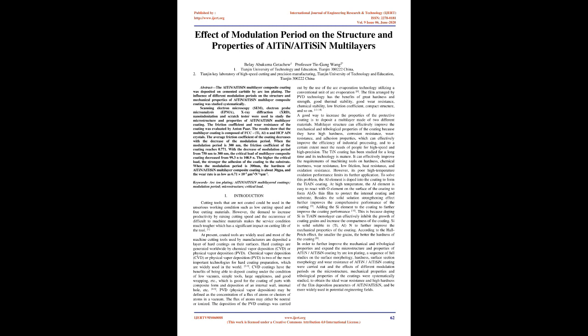The TiN coating has been studied for a long time and its technology is mature. It can effectively meet the requirements of machining tools on hardness, chemical inertness, wear resistance, low friction, heat resistance, and oxidation resistance. However, its poor high-temperature oxidation performance limits its further application. To solve this problem, the Al element is doped into the coating to form the AlTiN coating. At high temperature, the Al element easily reacts with O on the surface of the coating to form an Al2O3 thin film to protect the internal coating and substrate. Besides, the solid solution strengthening effect further improves the comprehensive performance of the coating.